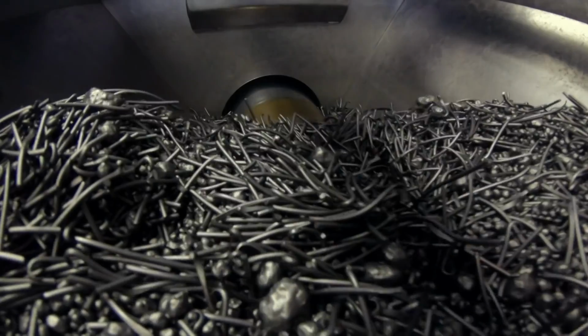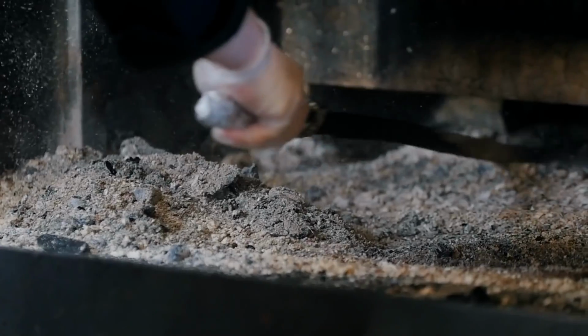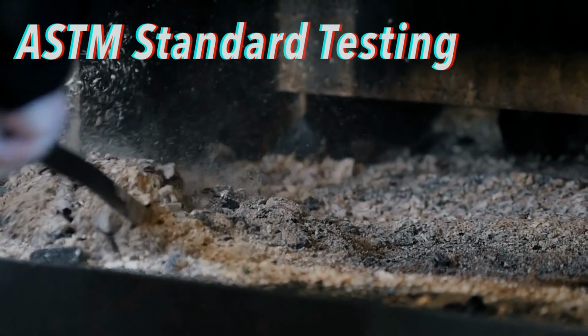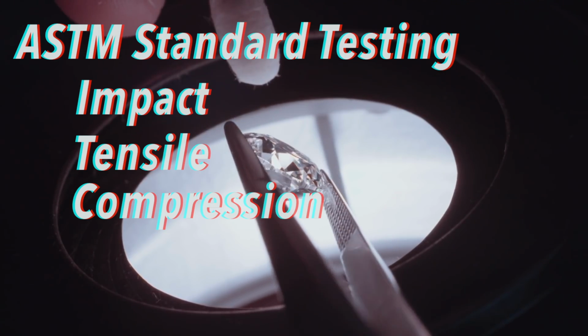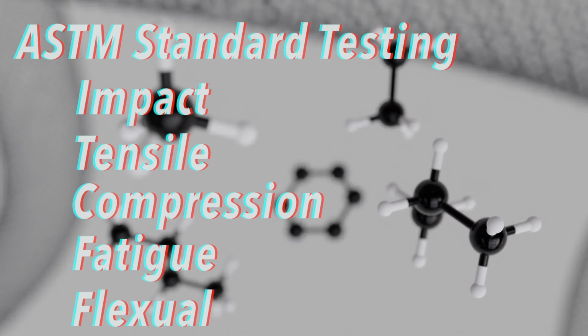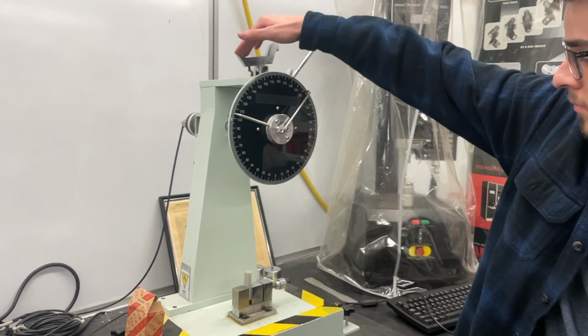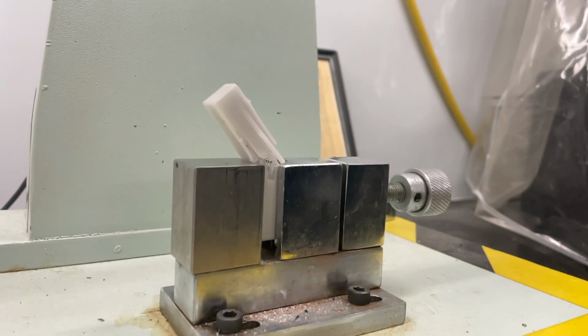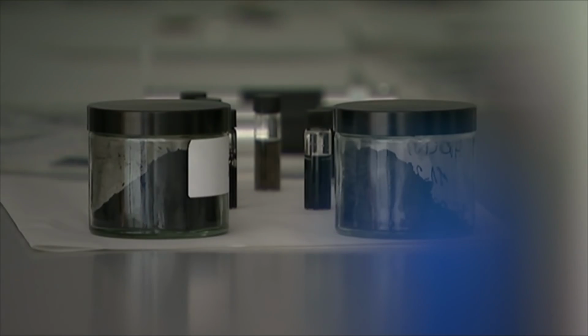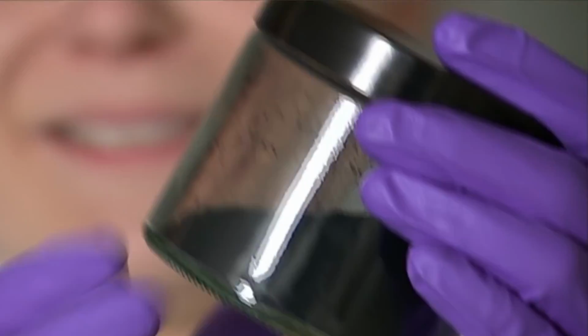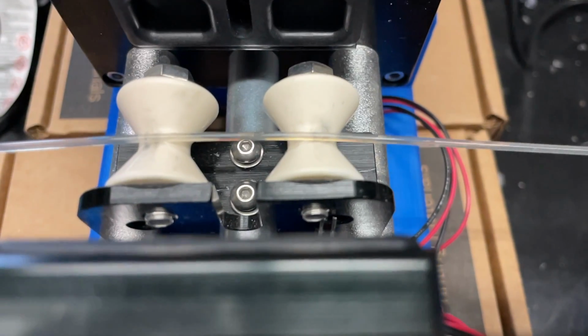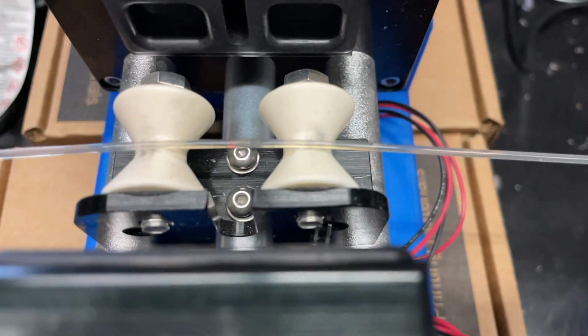The main objectives of our recyclability study were to extrude 10 generations of material, printing test pieces from each generation. Test pieces were all made to ASTM standards, and we conducted impact, tensile, compression, fatigue, and flexural tests. From this testing, we were able to determine how the material properties will change over time. For our composite study, we mixed carbon nanotubes with virgin PETG material. Throughout both of our studies, we used our horizontal extruder to produce printable filament from plastic pellets.